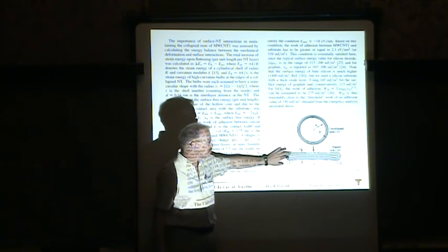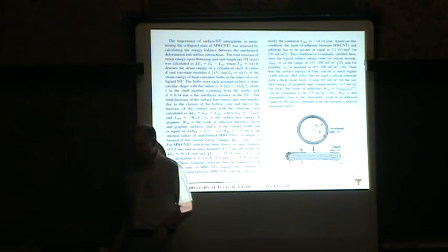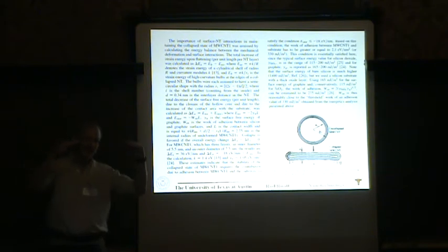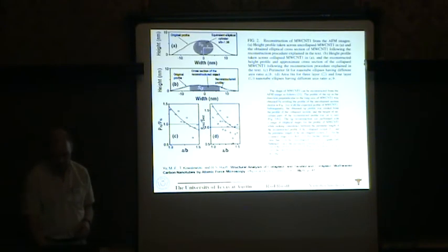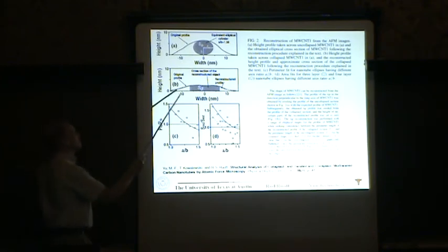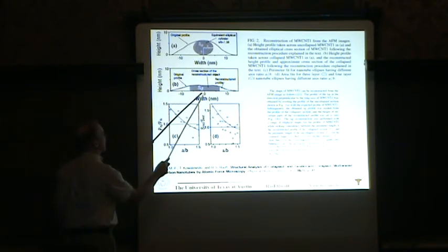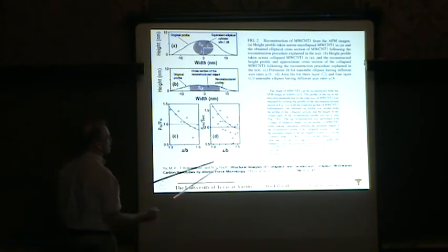And then when you add those up, you can consider that the tube might be stable or metastable to collapse, depending on the overall diameter and the number of shells, either in free space or when contacting the substrate, if you somehow knew the adhesion energy to that particular substrate. And so with this method of constraining the perimeter and our knowledge of the thickness, we could unequivocally show that this was a three-walled tube of a particular diameter if it were not collapsed.